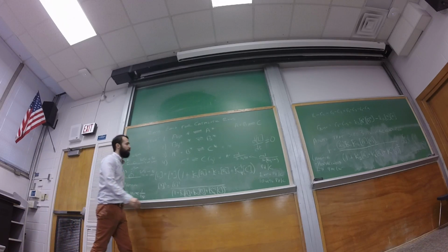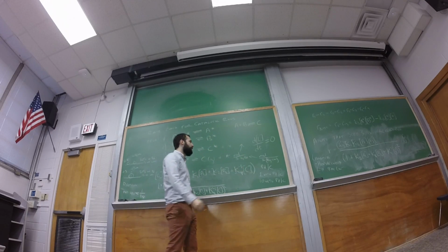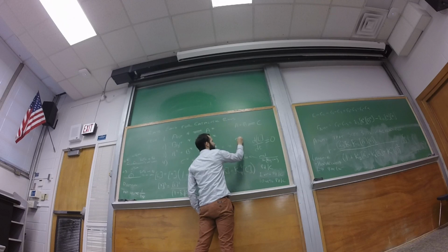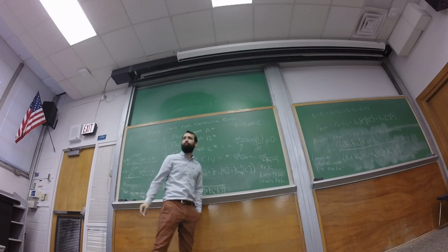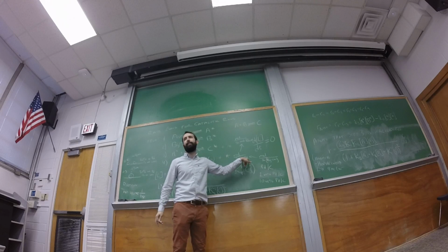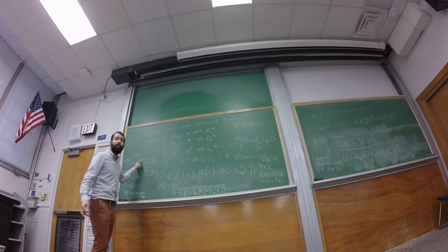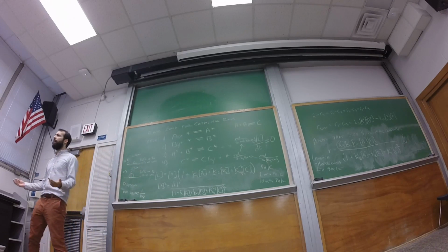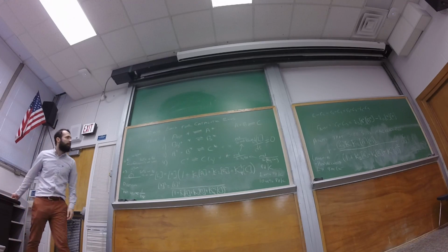Right, so instead of using the total mass of my active material, normally at this point you switch to moles. I'm not quite sure why, probably just because the mass is extremely small. Moles of palladium at the surface. And that's fine. We can convert between all of those things. If I know the mass of my catalyst, I know the molecular weight, so I get the moles of palladium. I know the dispersion, so I just multiply it or divide it by the dispersion, and you get the amount of surface palladium atoms.